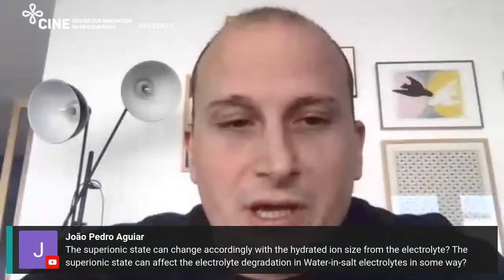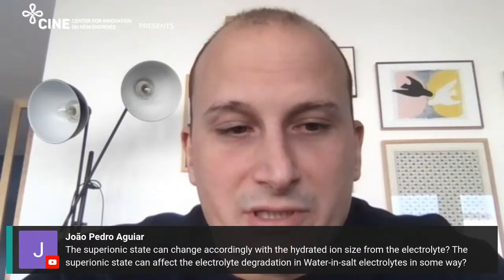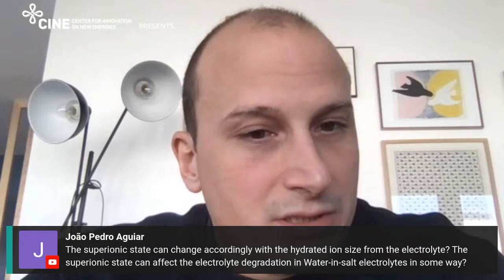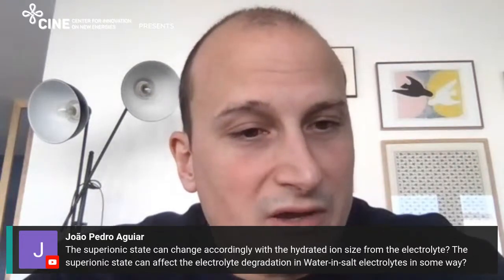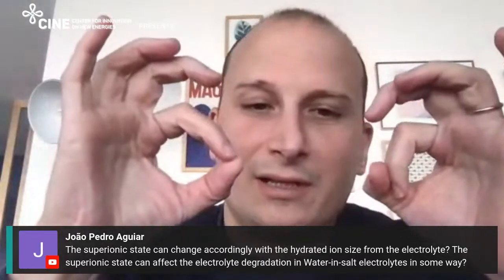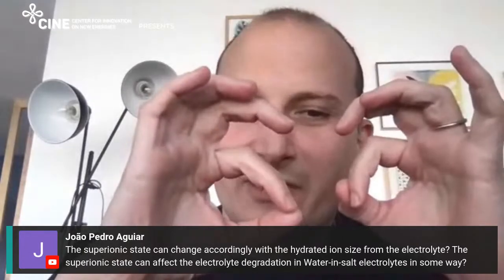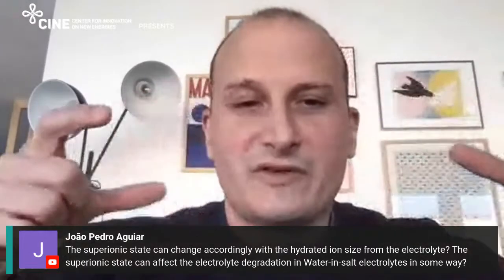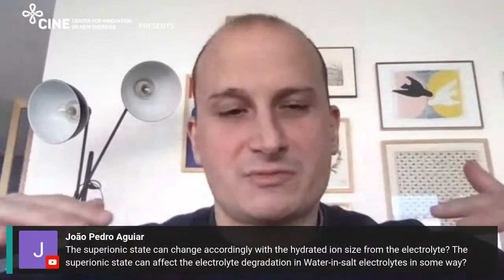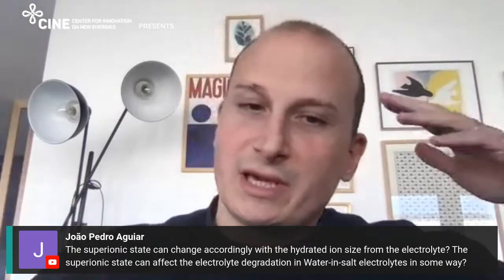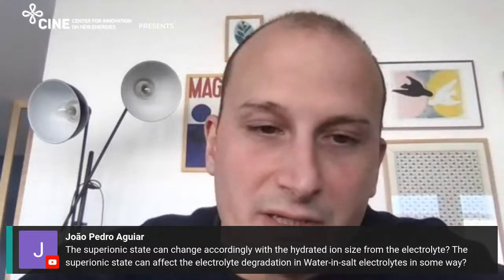Okay, so the first question, for sure. Here we did not have water, but of course, if you have water, it will screen the interactions further. So you clearly have a kind of superionic state when you have hydrated ions. But I would say that the larger the size of the ions, the more chances you have to reach a superionic state. Because if you think of lithium, for example, lithium is very small, and so the Coulomb repulsion between two lithium ions, even if they are hydrated, can be very, very strong. While when you have this imidazolium, whether solvated or not, the charge is more delocalized. So in the end, I think their size will impact this superionic state a lot.